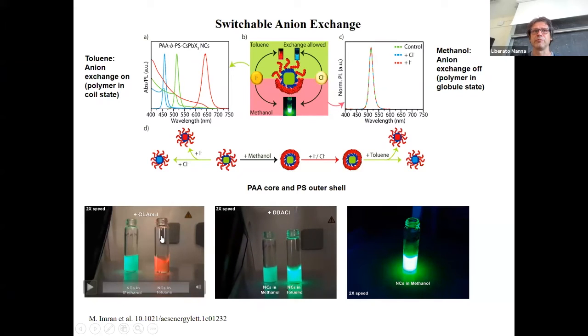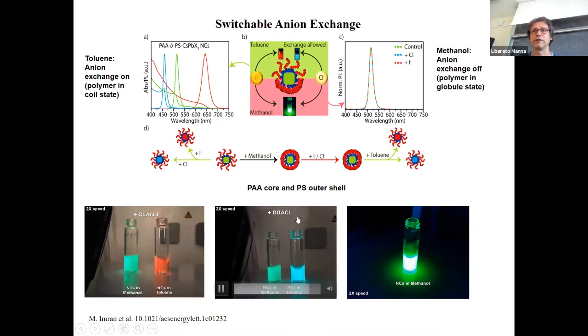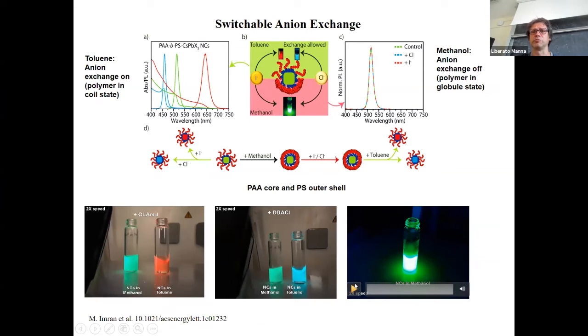This is the same thing, but starting from cesium lead bromide and adding a chloride additive. And you see again that in toluene you trigger an anion exchange easily, whereas in methanol this is completely suppressed. You can also attempt an anion exchange in methanol, for example, and you will see that this is not occurring, okay, because the polymer is in the globule state.